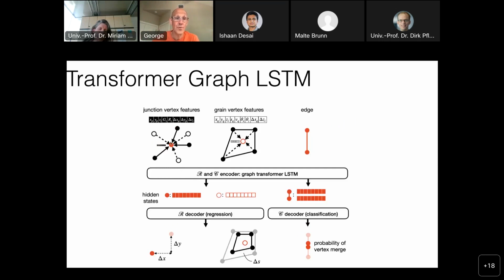And the features for junctions, or for points, are basically the position, the height, the temperature at this position, and the change with respect to the previous time step. So we also maintain the changes. This is the input, and then we want to predict the next change. And these are the grain vertex features, in which again we have the center of mass of the grain, the orientation of the grain, the excess area, the change in the area, and how much it moved vertically. And then for the edges, we have the length of the edge and the features of the two nodes.